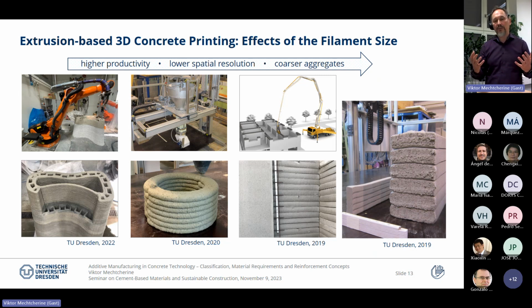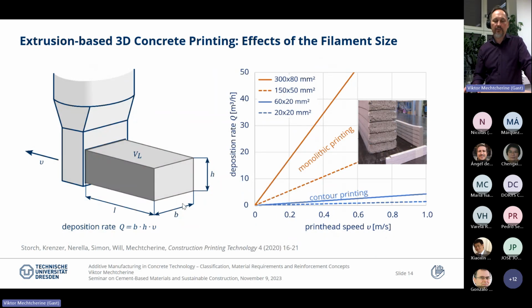real concrete, right? But you lose the spatial resolution, so you must restrict yourself to, let us say, more regular geometries. You are not that free in this. So this is quite an important distinction, and I want to elaborate on it a little bit more. Going for larger filaments means that you have a quite pronounced increase in productivity, and this is very important in construction. I have here a little graph which shows this quite clearly: going to larger filaments and keeping the same speed of deposition, you place much more material per time unit, and it's quite an important subject.